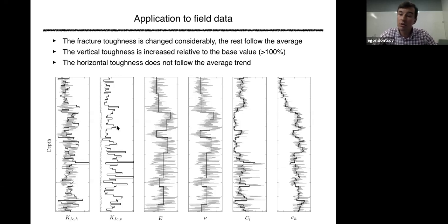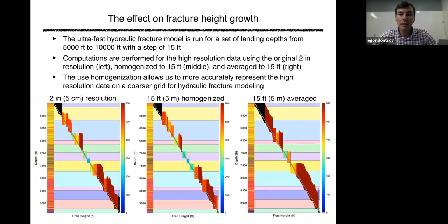So it depends on what stress model you use. It depends on many factors, but in general, the vertical toughness increases relative to the base value, on the order of 100%, okay? Or maybe more, it depends on the resolution and everything, right? So that's the biggest implication. And here, another thing that we did is we tried to use it just as a step towards validation, to see what's actually the implication for fracture geometry.